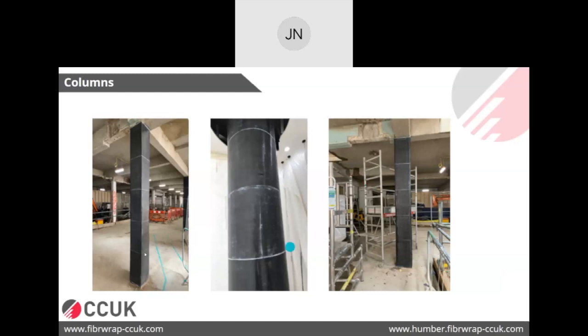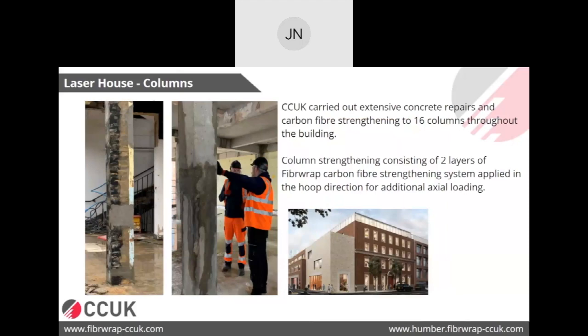So that's in a nutshell the design concept of strengthening using carbon fiber. The same theory you can use on square and rectangular columns, but you have to round off these corners to a minimum radius of 20 millimeter, and also the aspect ratio has to be less than 2. Because if it is more than 2, then you have to go with the more complex analysis of combined axial and bending.